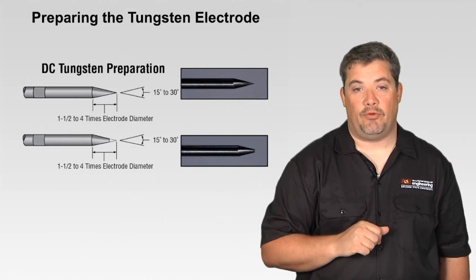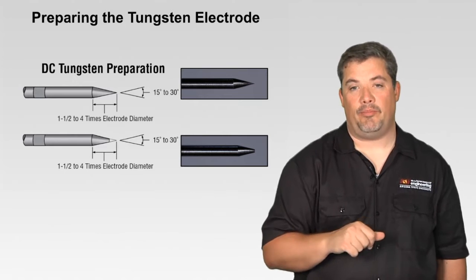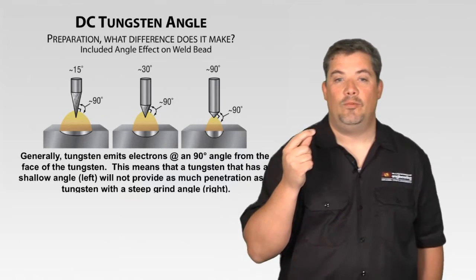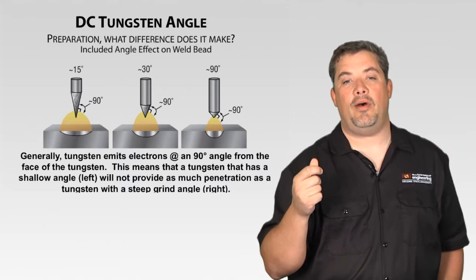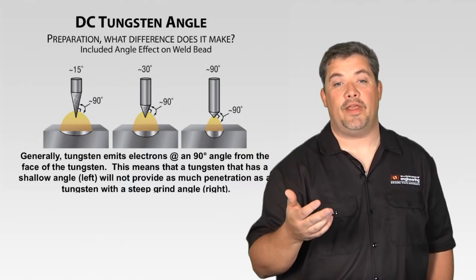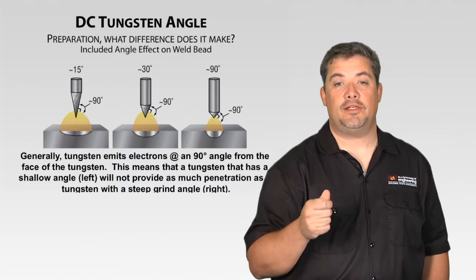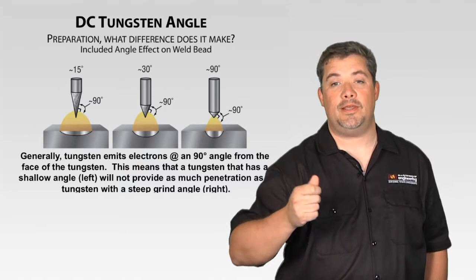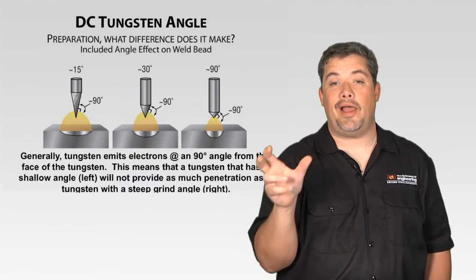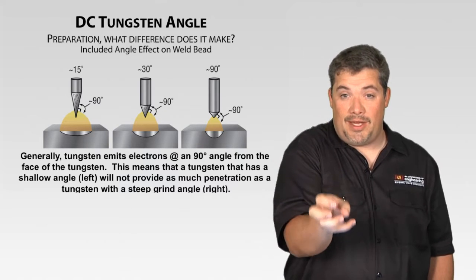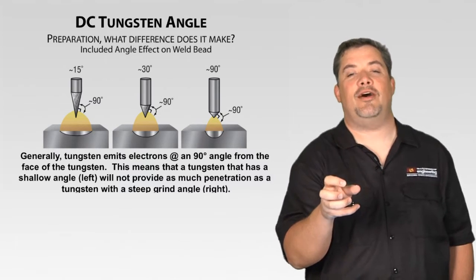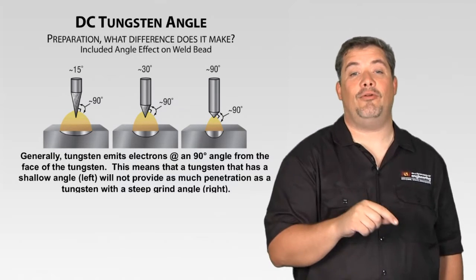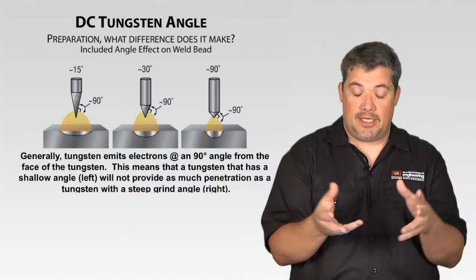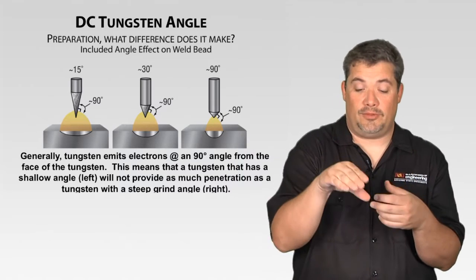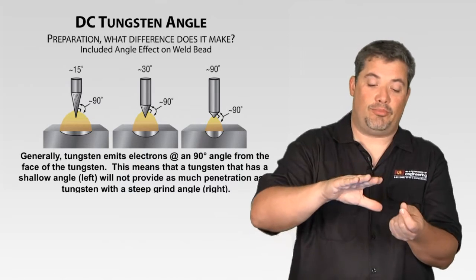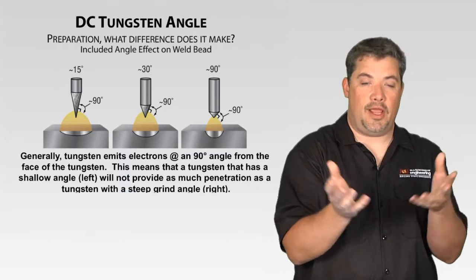So DC, straightforward. Sometimes in DC, they like to blunt it back. And the reason is that when those electrons come off of that tungsten, they come off generally at a 90-degree angle from the face of the tungsten. So different tungsten angles will give you different bead shapes. So you can see on the right, that 90-degree included angle actually makes for a narrower puddle, so it's concentrating a lot more heat into a small spot. Well, when I do thin stuff, I actually probably want to use that 15-degree included angle so that arc energy is spread out to give me more control on that really thin material, because if it's really focused, I'm punching a hole through it. But if it's spread out a little bit, it gives me a little bit more control to actually make a nice small bead.